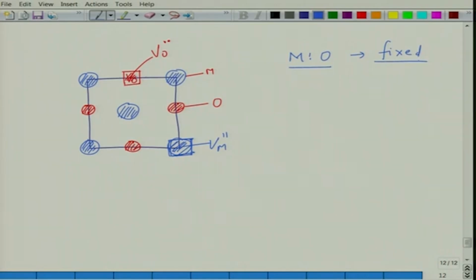Okay. So, this is called a Schottky reaction, and this reaction generally happens at the outer or inner surfaces or at dislocations, wherever energetics permits it, and generally these metals and oxygen diffuse out of the system until you reach equilibrium. So, this is the equilibrium defect. You will have some of these defects always present thermodynamically in a system. We will do the thermodynamics later on. And these defects are generally preferred when anion and cation are of equal or comparable sizes. So, this is for MO.